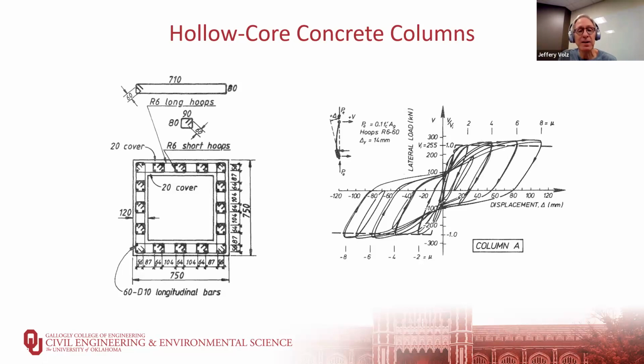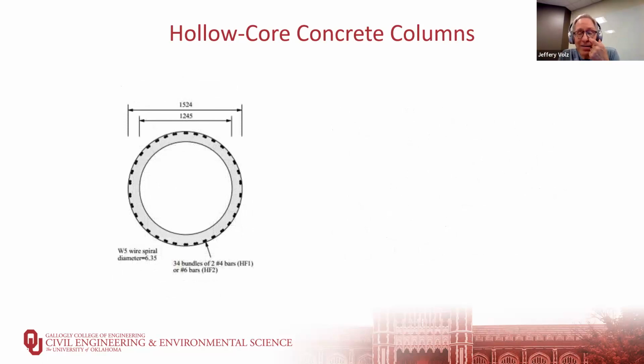This is a typical hysteresis loop. It's important to recognize that the area within the hysteresis loop is energy absorption, which helps us in these dynamic hazards that can impact our structures. So the more consistent and without degradation the hysteresis loop we have, the better the behavior. We see that this reinforced concrete hollow core column is behaving very well, up to a ductility ratio of 8. But that reinforcing cage takes a lot of manpower to build because of having to tie it together.